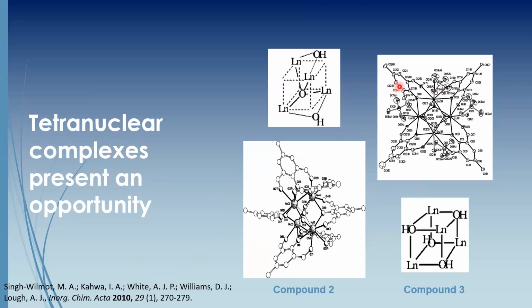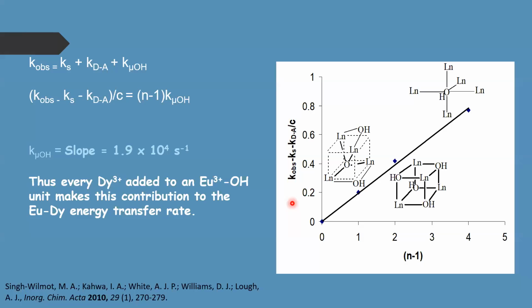So we did different types of clusters where the lanthanides were connected by various what we call supramolecular glues. Those are small ions that connect the lanthanide ions. And we studied the impact of using various supramolecular glues like oxides and hydroxides to connect lanthanides in various geometric predispositions. And we were able to do some calculations that allowed us to determine the contribution to the interaction between, say, europium and another lanthanide, dysprosium, that are connected by hydroxide units. And we were able to calculate the contributions from the energy transfer rates.